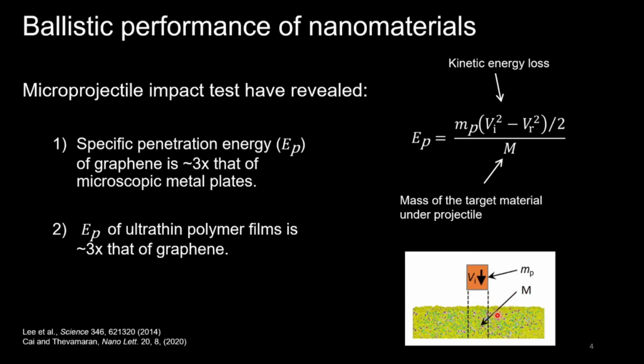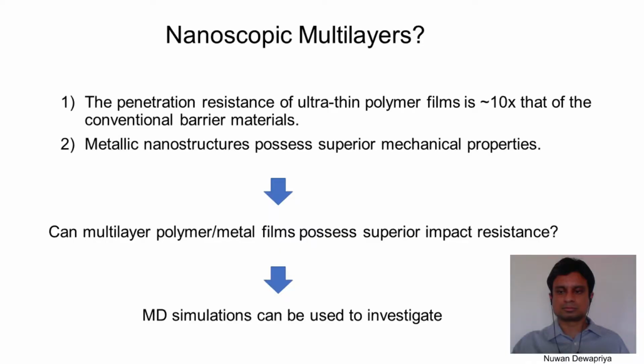Impact tests of ultrathin polymer films have revealed that their EP is significantly higher than that of graphene. This improved ballistic response can be mainly attributed to the lower entanglement density in the near surface region, which leads to a higher plastic deformation of thin polymer films. The experimental results have shown the superior impact resistance of ultra-thin polymer films.